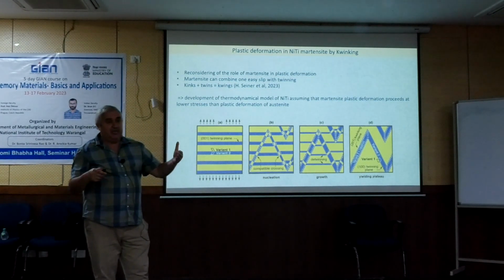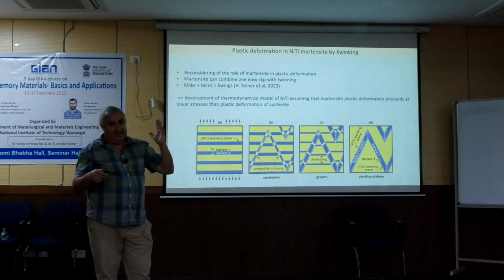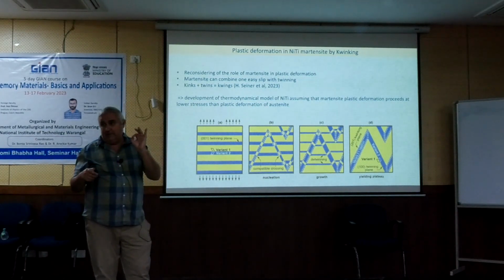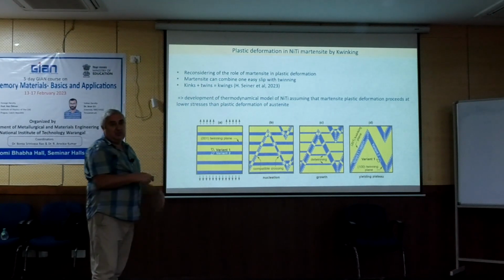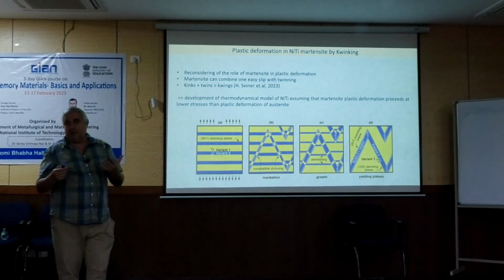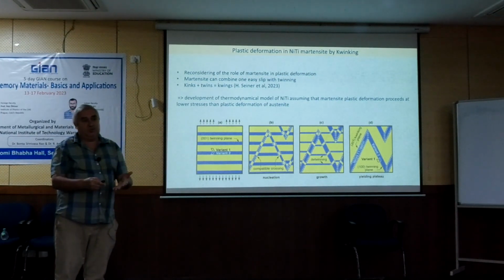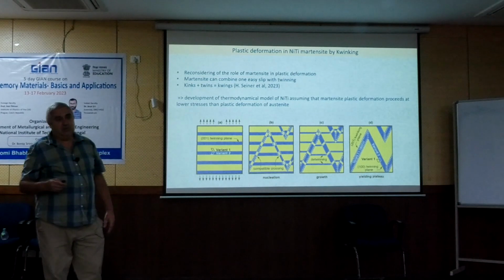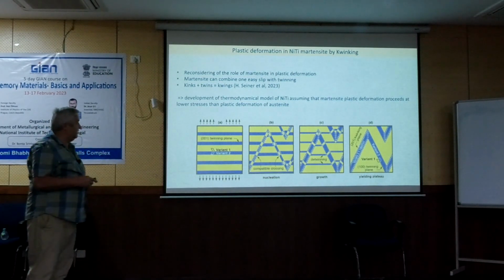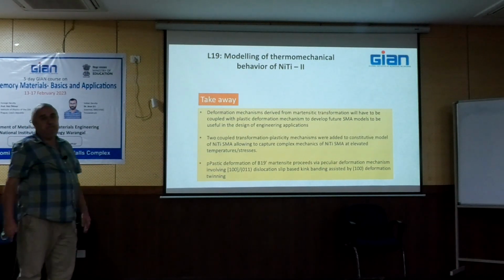If I do precipitation, if I heat treat the material at 300 degrees C for 1 day, I introduce nano-sized precipitates, they will block the dislocation motion, they will block this mechanism. So suddenly the things which were obscured become clear. And all this has to be introduced into the model in some suitable mathematical form that it can be used for treating general problems. Yeah. 2 slides.